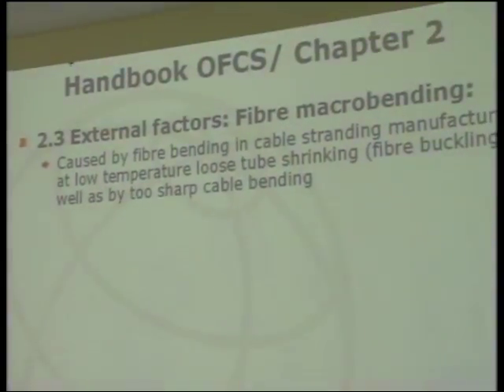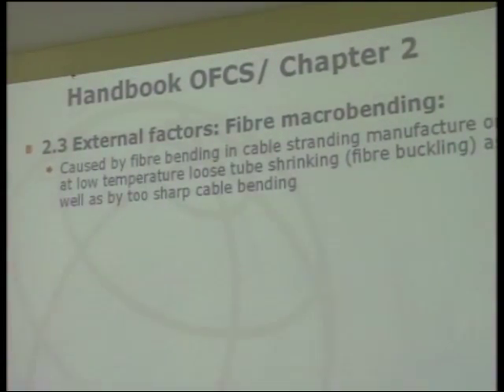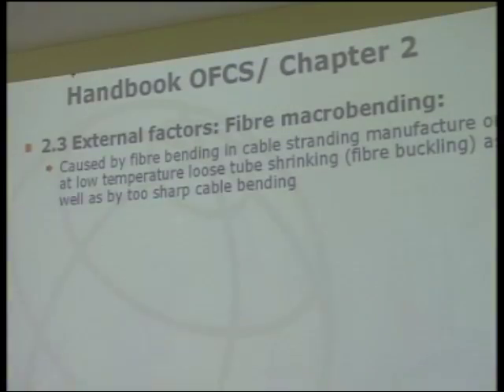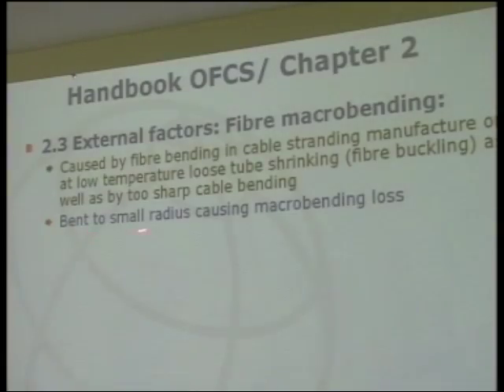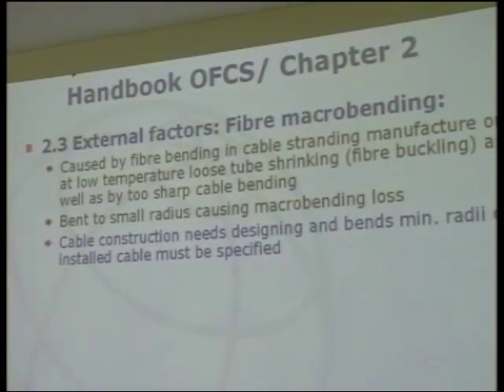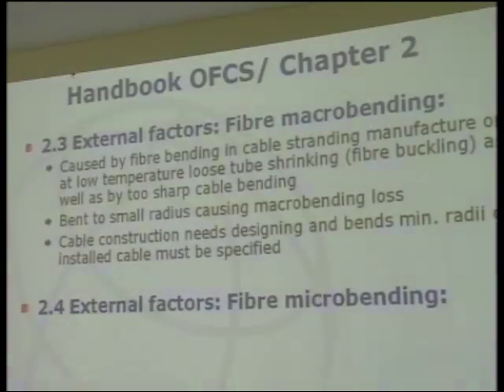the fiber is shrinking at low temperatures, and because of that, you get a kind of fiber buckling, additional storage of fiber over lengths in the loose tube, which is causing a macro bending effect because the fiber inside the tube will be at a short bending radius. This may add to the bending issue. But also, of course, a possible sharp cable bending will add to this problem. So bending to too small a radius is causing macro bending, that's clear. And the cable construction needs a design of bends, a minimum installation radius of the cable must be specified. So this is on macro bending.